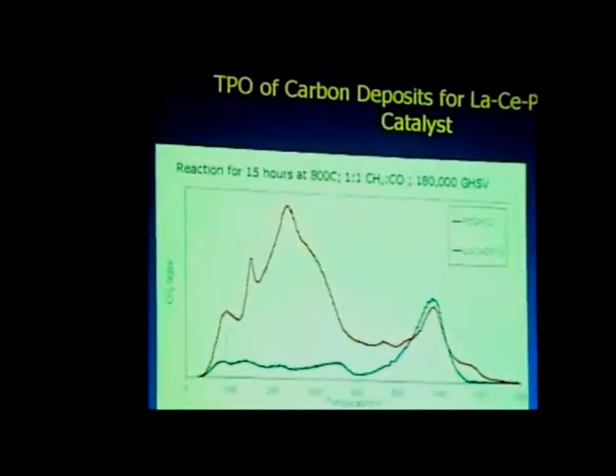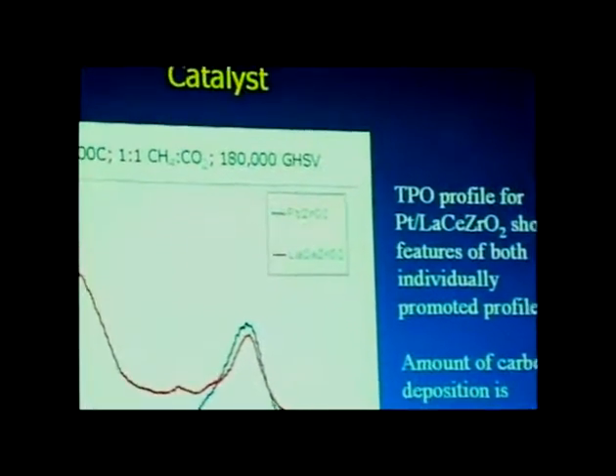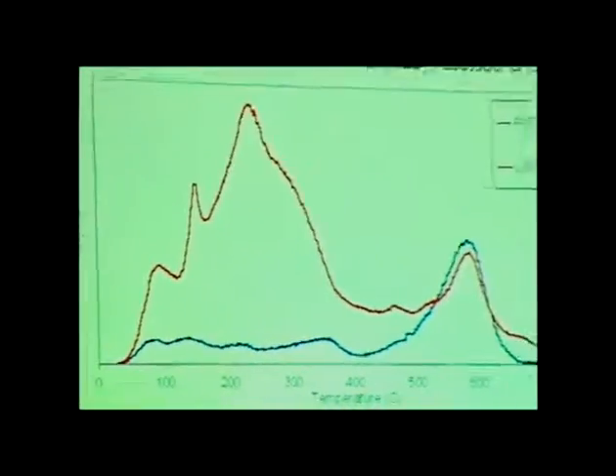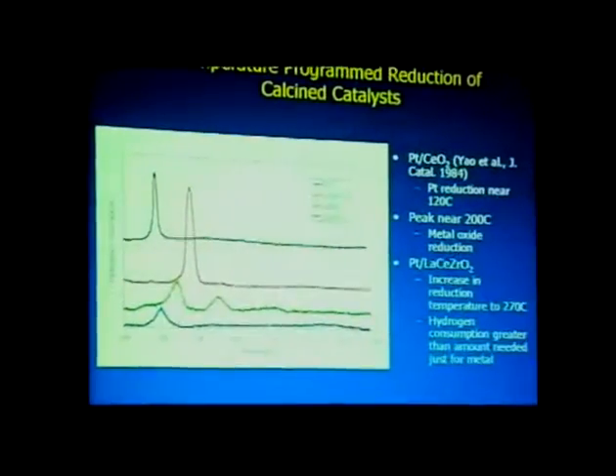If you look at the TPO for carbon deposits on the lanthana ceria promoted catalyst, and this is the TPO here, it's been expanded so you can see the regions. You see that you have features for both of the individually promoted catalysts. You have the low temperature peak and the high temperature peak. And the amount of carbon deposition for this material lies between that of the ceria promoted and lanthana promoted catalysts.